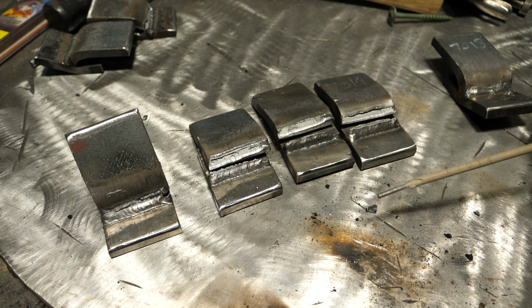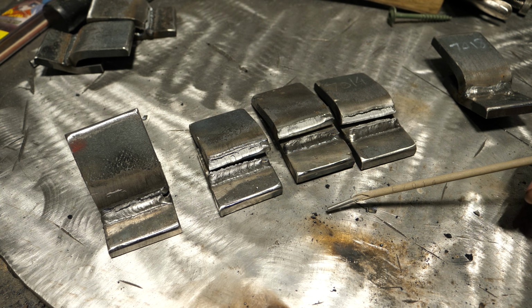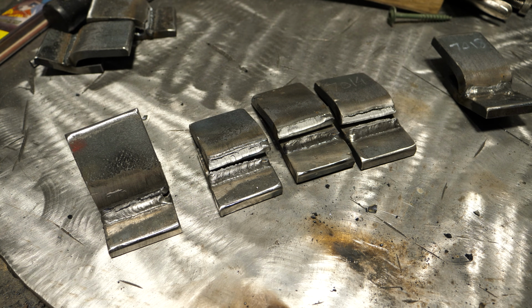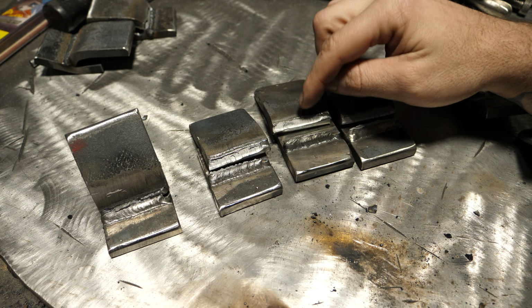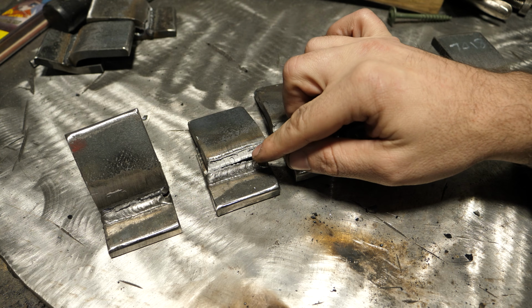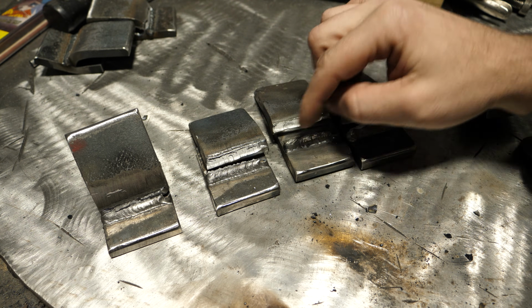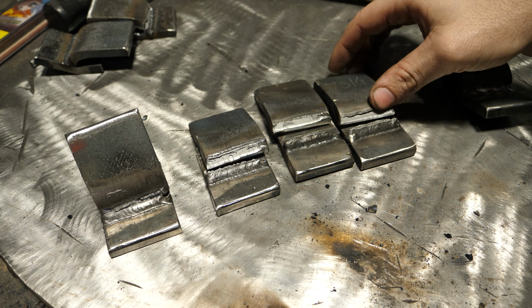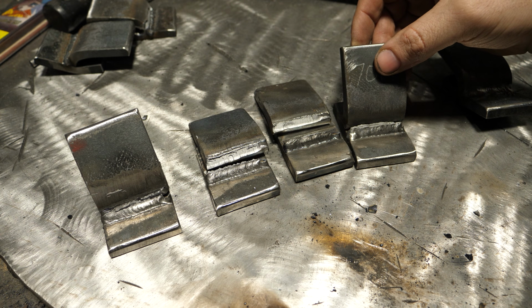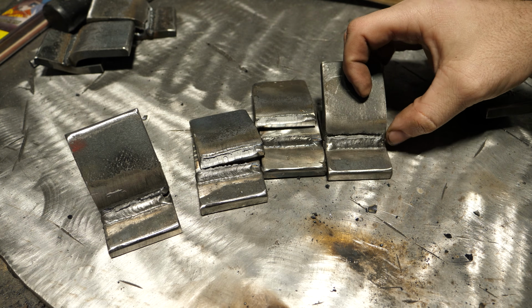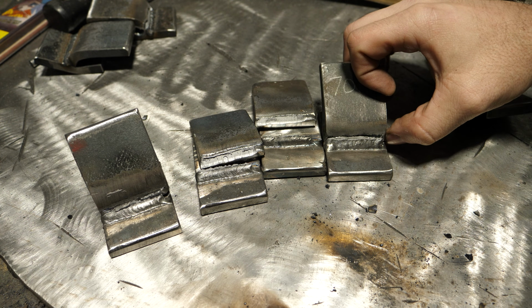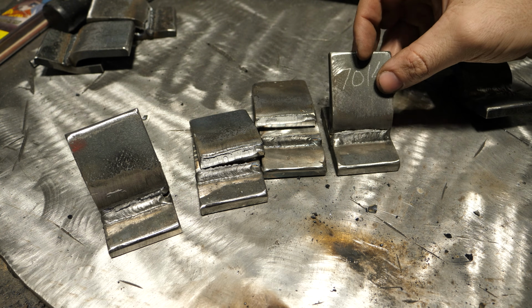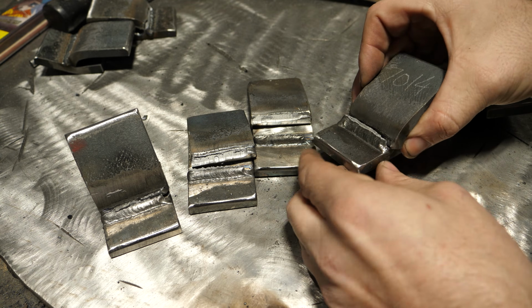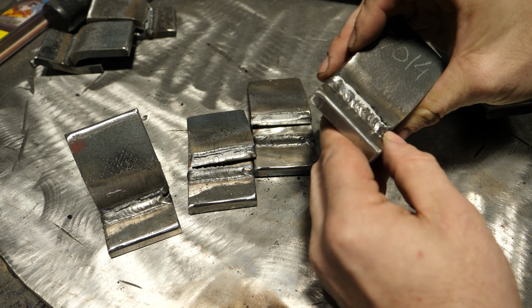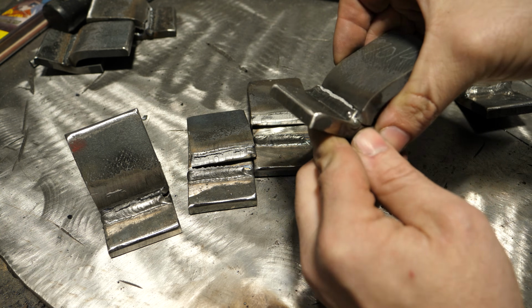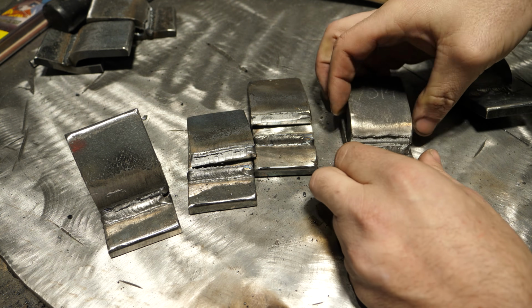So let's talk about what we have here. All of these broke literally in the same manner, okay? They all tore the weld off of the material. So it looks to me like whatever the weld penetrated separated directly from the material, which is interesting. It's hard to say, but it's entirely possible that in all cases the crack or the tear started down here where there was the least amount of weld metal. And on a lot of these, like you look at this corner, it isn't even blown out or anything. That's about as good as you can get at a stop without a runoff tab or something. If you look at that, still broke.